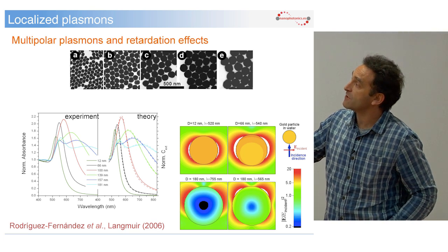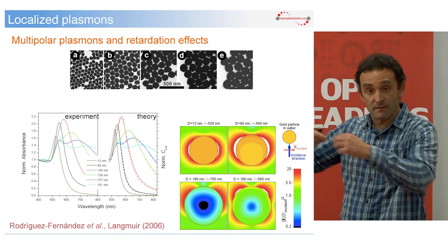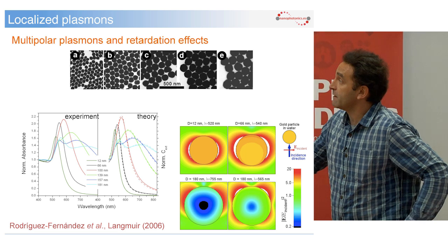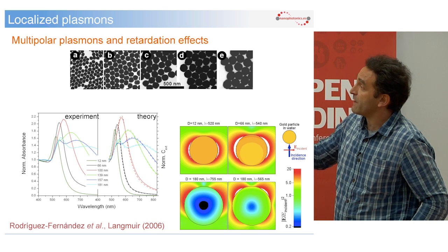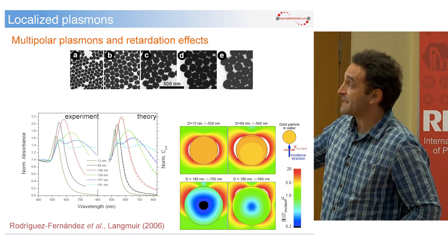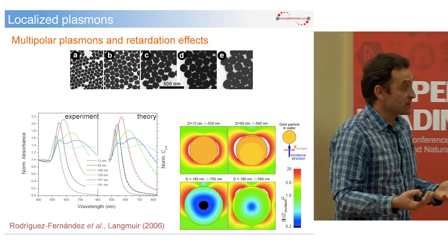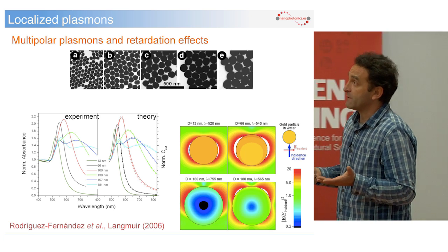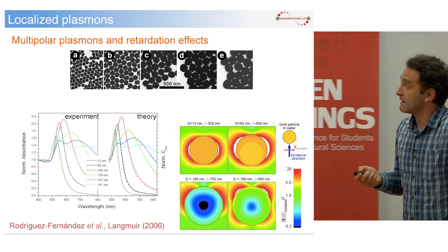And essentially, you have also the plasmon resonances, which have an associated electric field. As these conduction electrons move throughout the nanoparticle, then we'll set up, for example, in this case, a dipolar mode, and eventually it becomes more quadrupolar. So that's how you see here, when you go from a small nanoparticle to a larger nanoparticle, then you have a dipolar mode and eventually a quadrupolar mode. So the physics of the optical response of nanoparticles is by now well understood. And then many of these features we really understand.